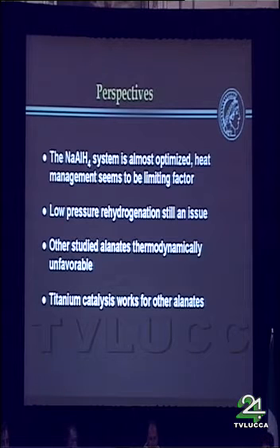I would say low pressure rehydrogenation at 50 bars is still an issue, because that would be very nice if one could achieve that. Other alanates which we have studied are unfortunately thermodynamically unfavorable. But the good news is that titanium catalysis works for the other alanates.